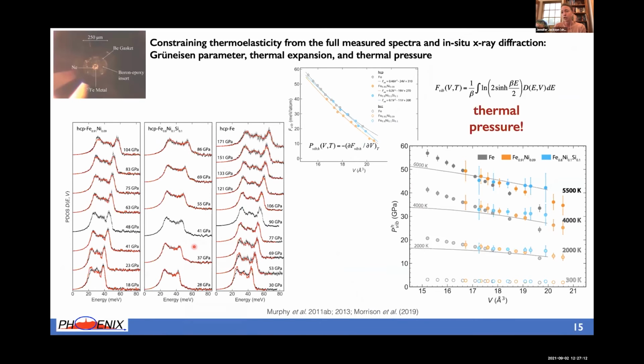So one example I'd like to show, in terms of using one of the COMPRES facilities, Sector 3 ID-B, and the nuclear resonant inelastic X-ray scattering technique, is to go beyond that of sound velocities, but to use the entire measured spectrum. And for iron, this entire measured spectrum and determining the unit cell volume dependence of that allows one to determine and constrain the vibrational thermodynamic properties, such as the Grüneisen parameter, thermal expansion, and thermal pressure. So other speakers have brought this point up during this workshop, the importance of understanding thermal pressure, not just from a material specific property, which is what we've done for iron and iron alloys, but to also measure this quantity in situ. So this will come up in just a couple minutes.